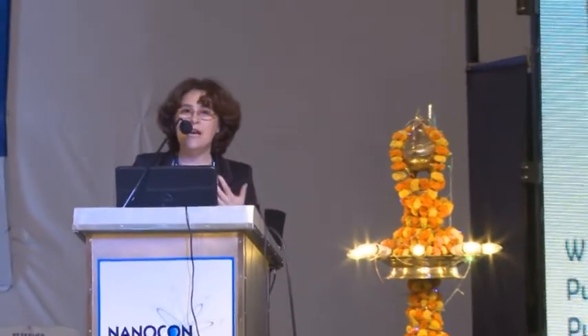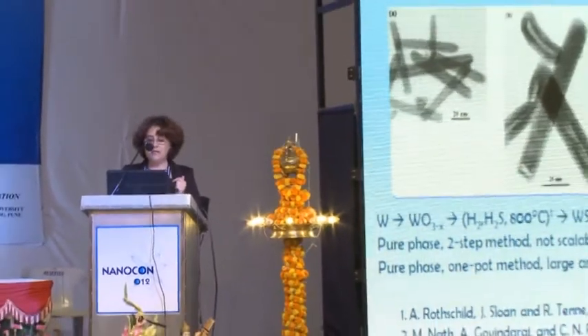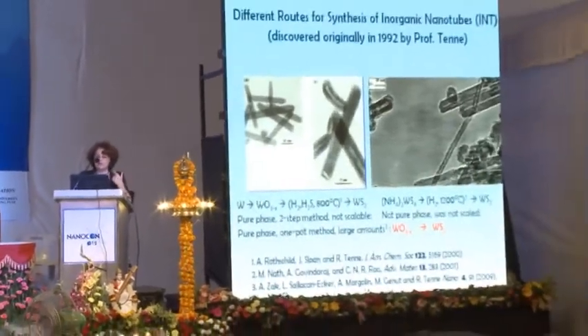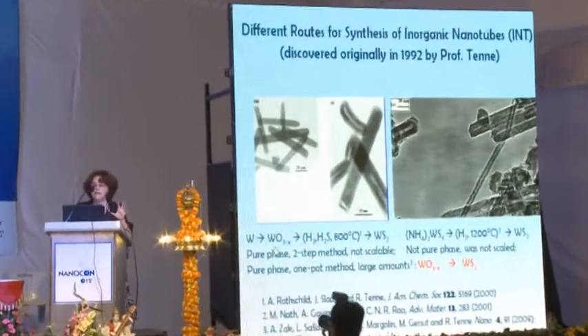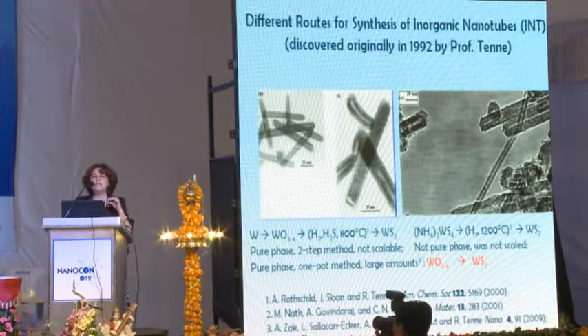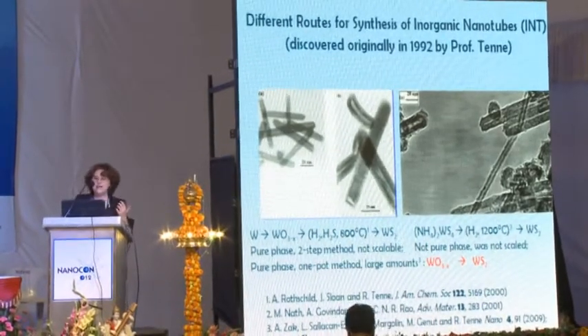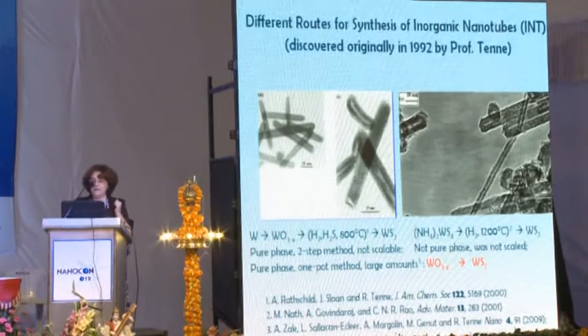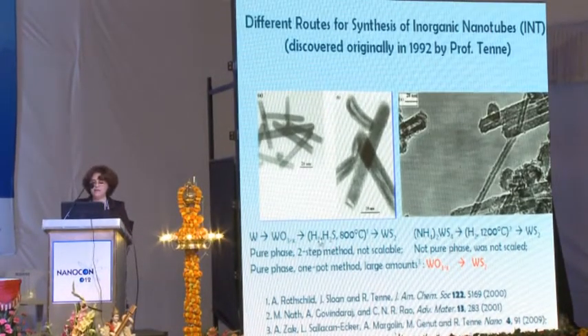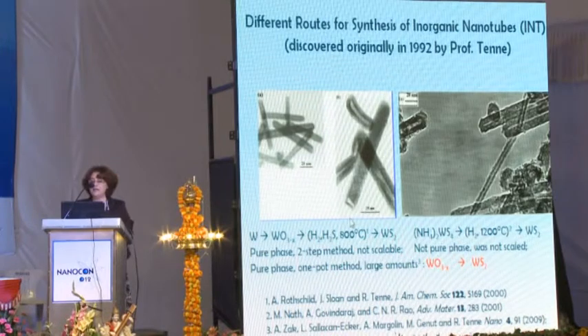On the left, we can see the experiment done in the laboratory of Professor Tenne, which resulted in a pure phase of inorganic nanotubes, but this process was not scalable. It was not possible to prepare enough material to study it further. This process started from tungsten, through a suboxide and a different setup, and afterwards these prepared nanowhiskers were sulfidized at high temperature in the presence of hydrogen sulfide and hydrogen, and beautiful nanotubes were obtained.